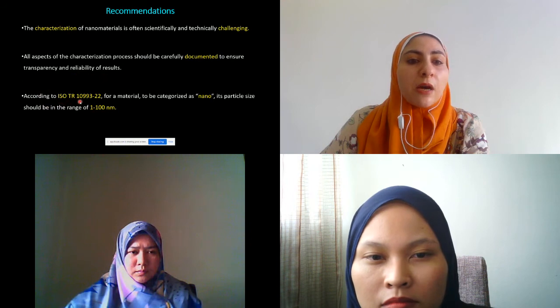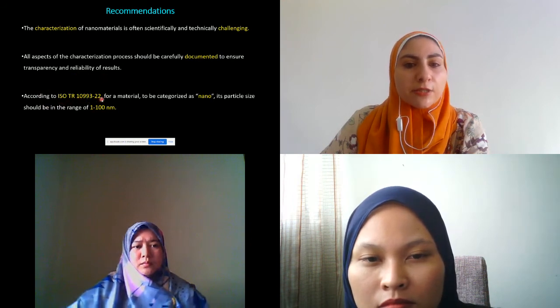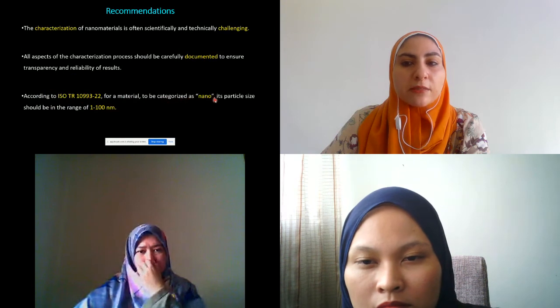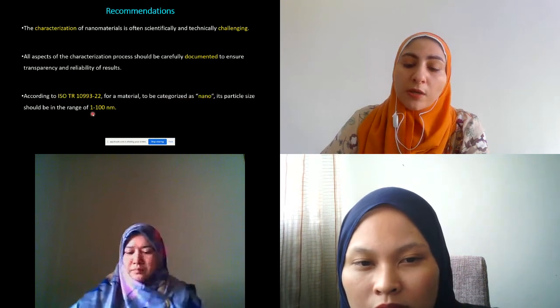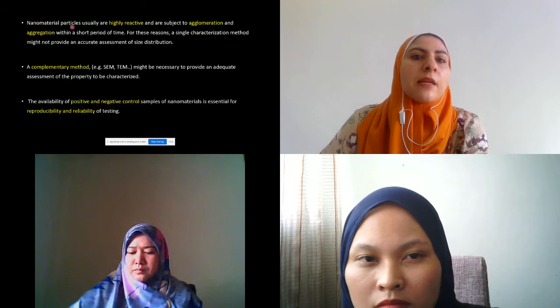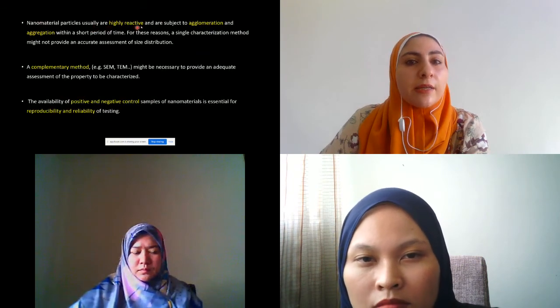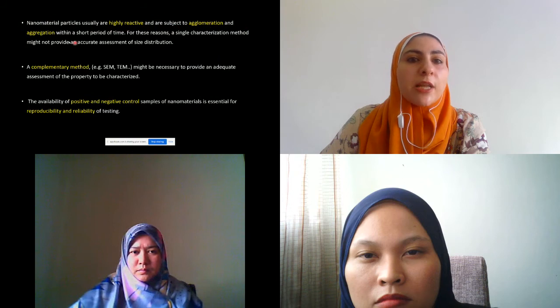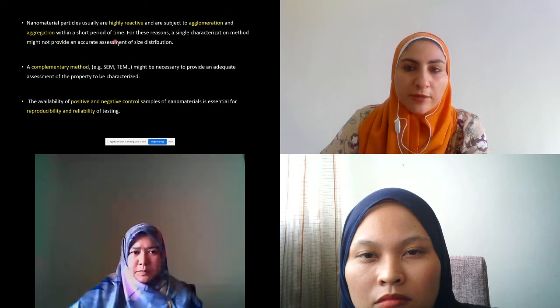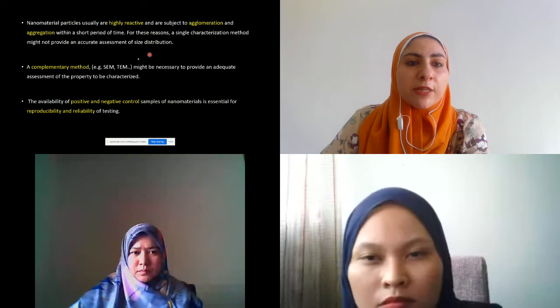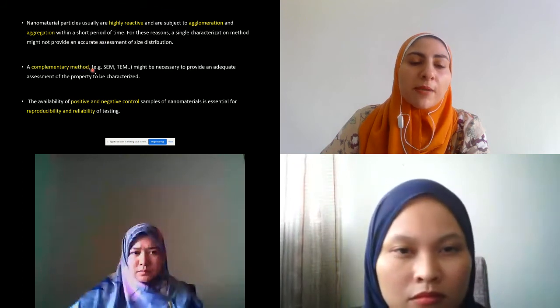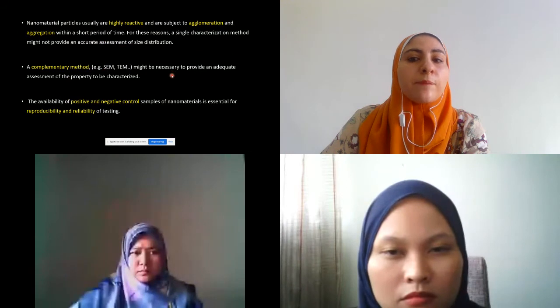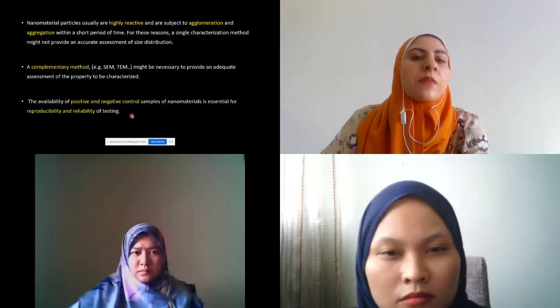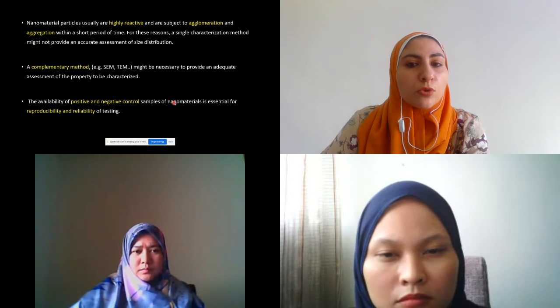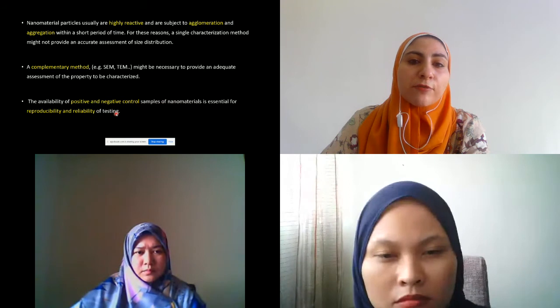According to ISO TR 10993-22, for materials to be categorized nano, it should be 1 to 100 nanometer and no more. Nanomaterials are usually highly reactive and subject to agglomeration and aggregation within a short period of time. For this reason, a single characterization method might not be enough. Complementary methods like SEM and TEM should be implemented in the studies. The availability of positive and negative controls for samples is a must for reproducibility and reliability of testing.